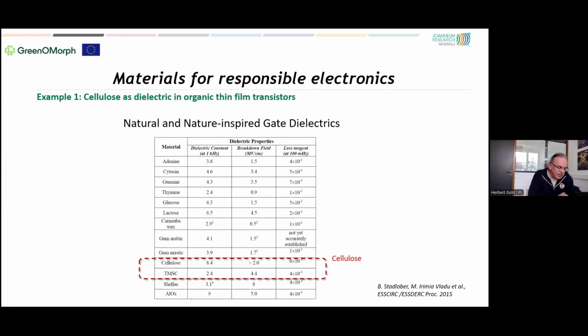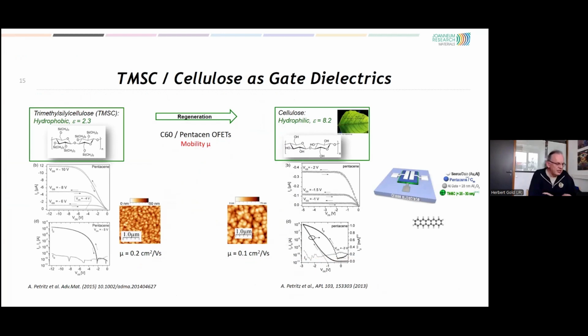And so let me show you an example from the past. It's quite some time ago when we tried cellulose as a gate dielectric for OTFTs. And this worked out quite nicely. So with the precursor TMSC, we had a nice performance. At that time, pentacene was the organic semiconductor of choice, and it showed a reasonable mobility for this material. So it was as good on the TMSC as it was on other dielectrics. And then this was regenerated to cellulose, because this was the goal of the demonstration, that this natural material would also work, and we could prove that it works.